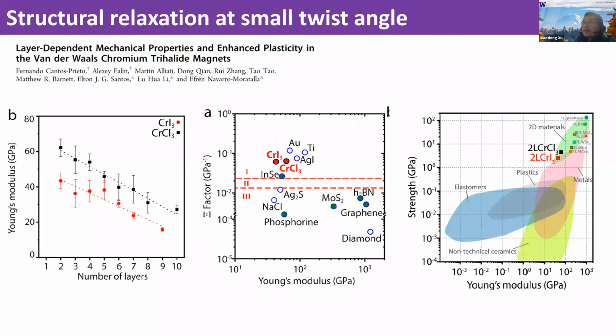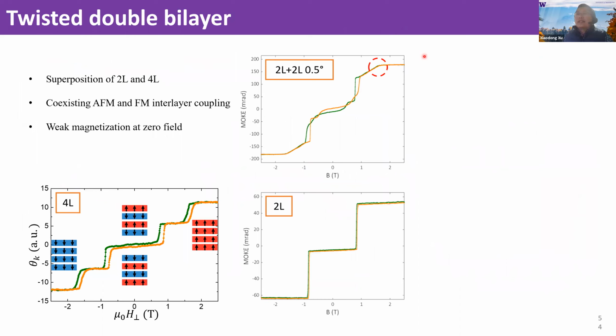Now, can we do better than that? The natural idea is, well, if we use multilayers, not the monolayer, but multilayers stacked on top of each other, because we expect multilayers will be stiffer than the monolayer, and the lattice reconstruction effect will be weaker. So if we go to multilayers, then there's a possibility we can achieve Moiré patterns. So what type of multilayer do we use? For example, can we use a double bilayer?